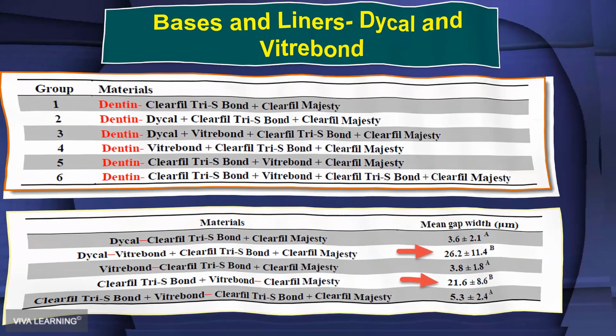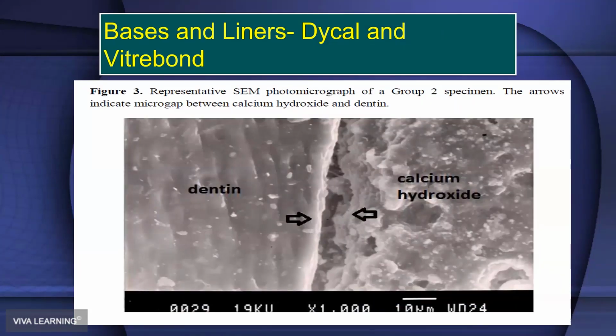So they actually looked at the void formation that they would see, and they would see a good amount of void formation that would form between the Dycal and the Vitrebond, between the Vitrebond and here, because that's the weakest link, and also here between the Vitrebond and the Clearfil Majesty, because again, this is wet, this is hydrophobic, and so this would be the weakest link here too. And at these really weak links, they would have these really big gaps. And big gaps, that's not a good idea at all. So basically, there's no bond between Dycal and Vitrebond at all. And between dentin and Dycal, there's no bond.